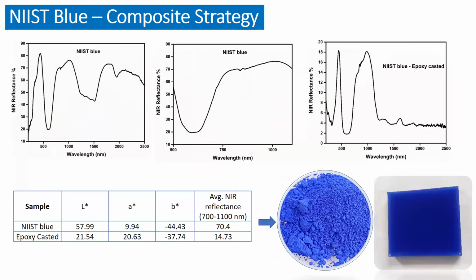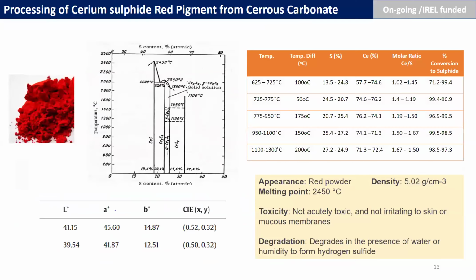And this is actually, as you all know, cobalt aluminate blue, and we developed the boehmite-derived, that means AlOOH-derived, blue pigment, and we found that the so-called NIIST blue pigment has an excellent IR reflectance in the critical wavelength range of 700 to 1100 nanometer.